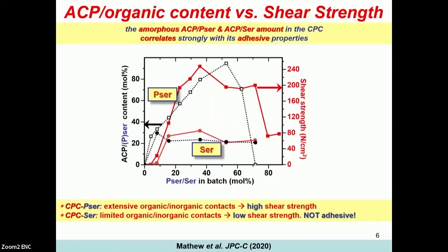Then we have also analyzed serine-doped cements, and for low serine contents, they work pretty much in the same way. There will be an amorphous ACP phase with serine molecules integrated. The problem is that when you increase the serine content, this phase doesn't develop further, so the TCP and serine just remains unreacted. And that is reflected here, as you can see, in a low shear strength throughout. So the serine-doped cements are not bone adhesive.